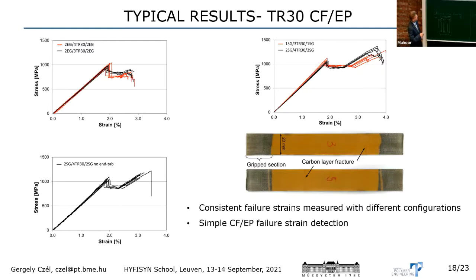And you can also see visually where the carbon epoxy layer failed in the specimen. So I think it's reasonably convenient. And yes, we've got consistent gauge section failures. And we were not shocked that some of them were close to the grips, because statistically, there is a chance that we must have some quite close to the edge of the gripping regions. It wasn't under the grips, just close enough, but we would have been surprised if we didn't have any of these. Unless our material is so bad that it has many defects in the gauge section. But even if there are strong defects, some could be closer to the edge of the grips. So statistically, it's okay to have some fractures near the grips.